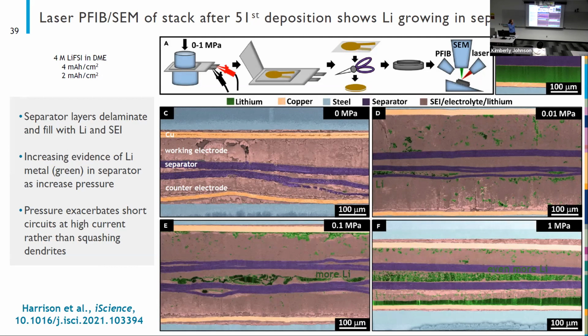So that all matches. If you remember, the electrochemical behavior looked better in the 1 megapascal cell. But personally, I think that's because it's shorted and we're not using lithium to apply the current. We're just directly moving electrons through the cell through the shorts. And so you might want to say that the 1 megapascal looks best from this, but we also know it's shorted. So I don't know that that is a reasonable conclusion. And so, the thickness being lower in that cell may only be because it's more shorted. So you aren't doing mostly electrochemistry, you're doing mostly direct electron transfer through the shorts. So it's tempting to say that's good, but I don't think it is.